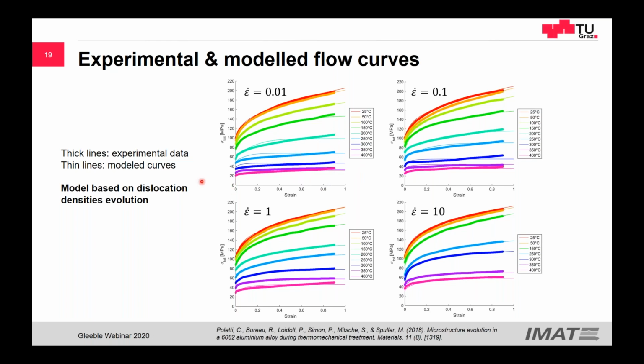We produced a model based on dislocation densities evolution. You can find all what I'm saying in our publications. And we found, of course, a high strain rate dependency at high temperatures, but not at low temperatures. This is what we expected. Of course, at low temperatures, you don't have strain rate sensitivity, or the strain rate sensitivity is very low.